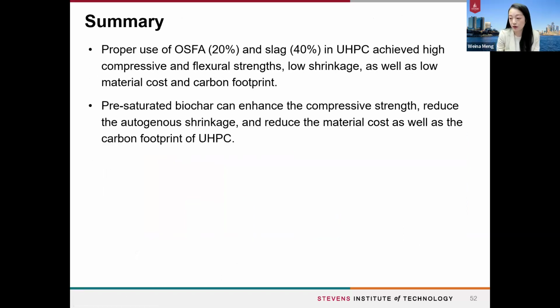So in a brief summary, the utilization of the waste materials in UHPC for sustainability should be treated case by case. So different strategies should be applied for different waste materials. For OSFA, we should use the slag to further improve the reactivity of the system and improve other properties. And for the biochar, as it has a very high amount of pores, we could utilize it as an internal curing agent to improve the overall performance of UHPC.